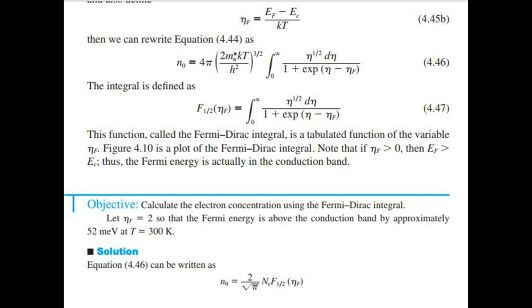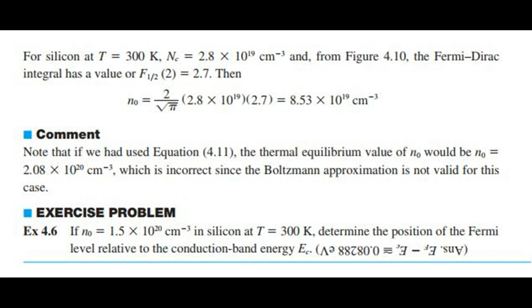Thus, the Fermi energy is actually in the conduction band. Objective: calculate the electron concentration using the Fermi-Dirac integral. Let eta_F equal 2, so that the Fermi energy is above the conduction band by approximately 52 millielectron volts at temperature 300 kelvins. Solution. Equation 4.46 can be written as follows. For silicon at temperature equals 300 kelvins, Nc equals 2.8 times 10 to the 19 per cubic centimeter, and, from figure 4.10, the Fermi-Dirac integral has a value of F1/2 equals 2.7. Then the result follows. Comment. Note that if we had used equation 4.11, the thermal equilibrium value of N0 would be N0 equals 2.08 times 10 to the 20 per cubic centimeter, which is incorrect since the Boltzmann approximation is not valid for this case.